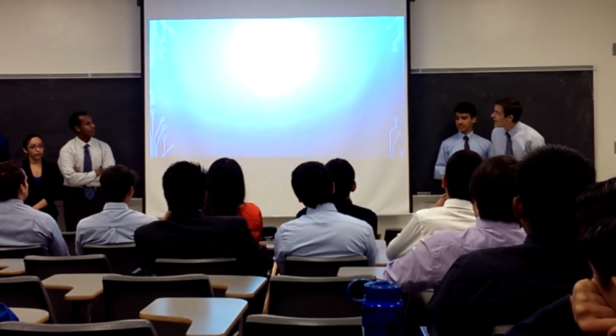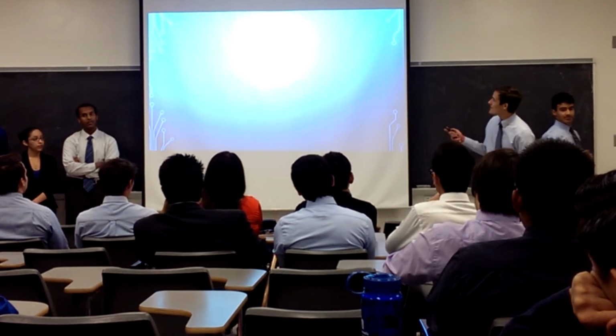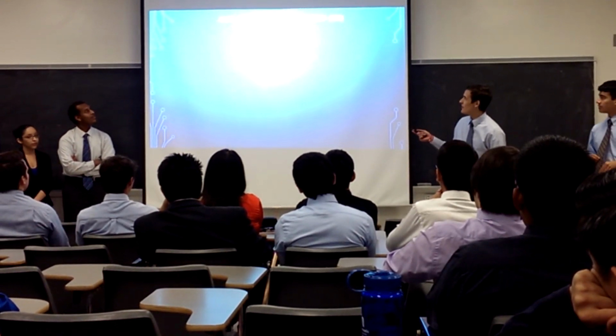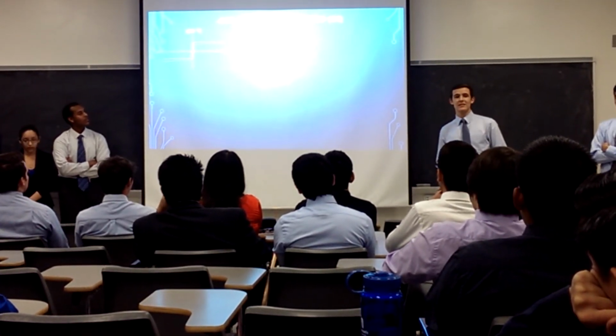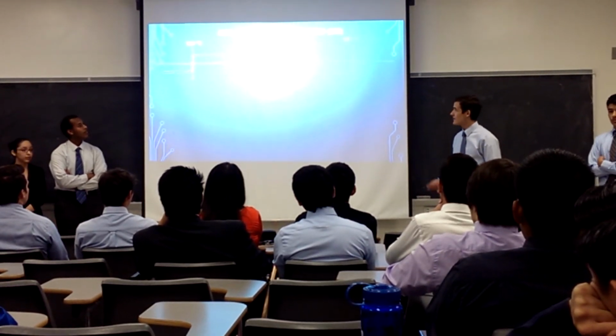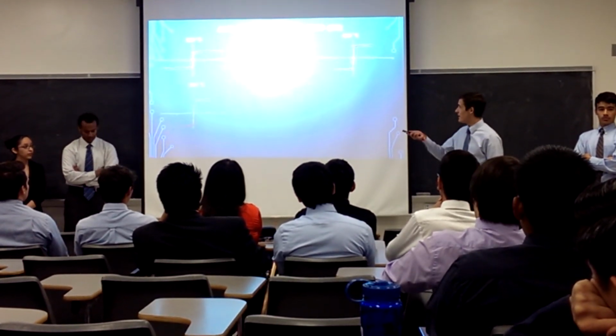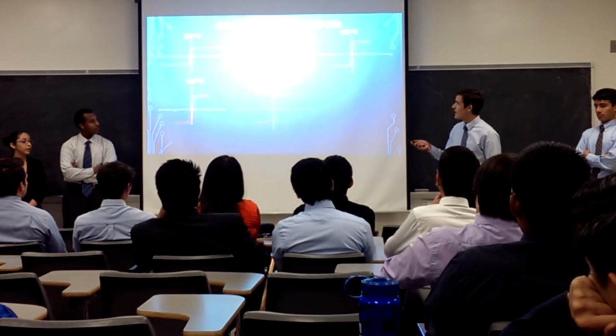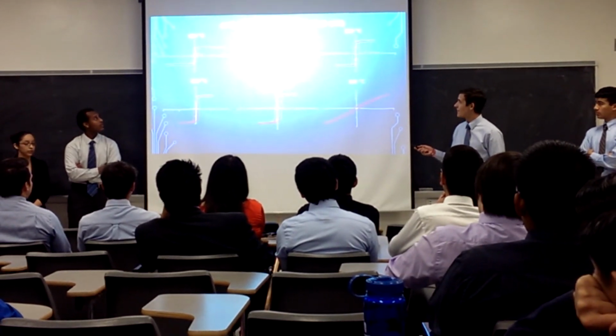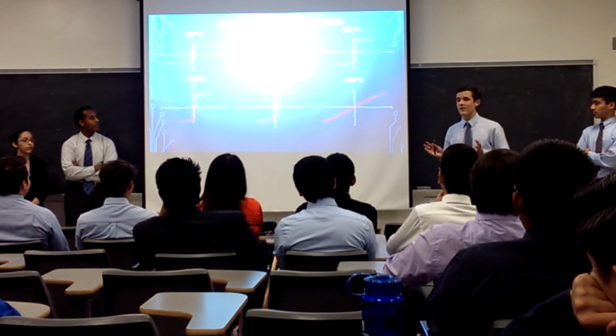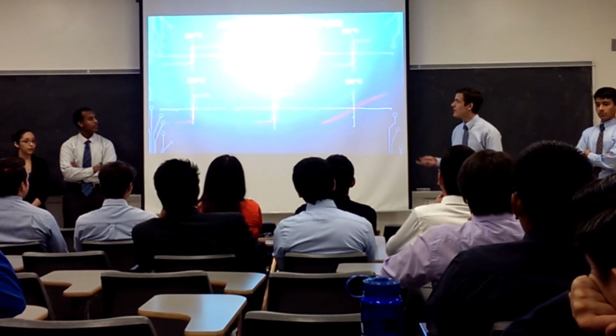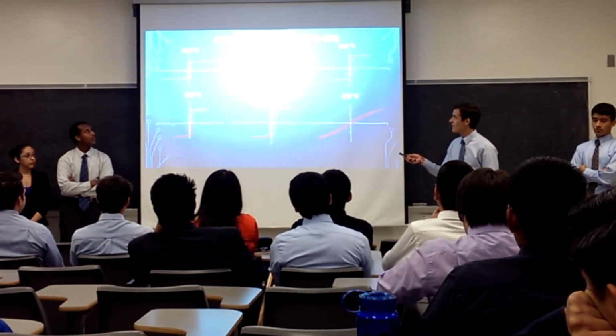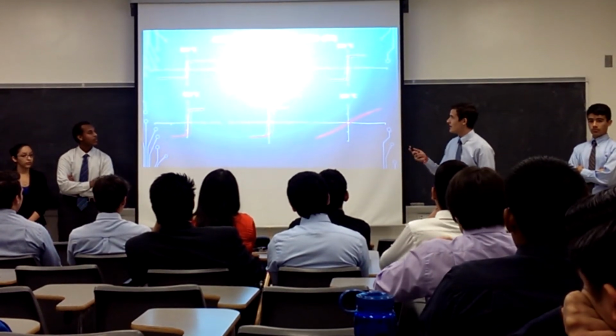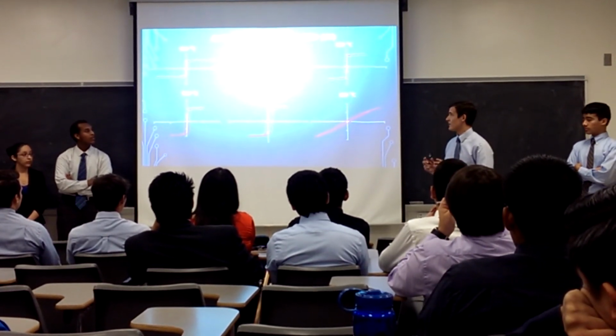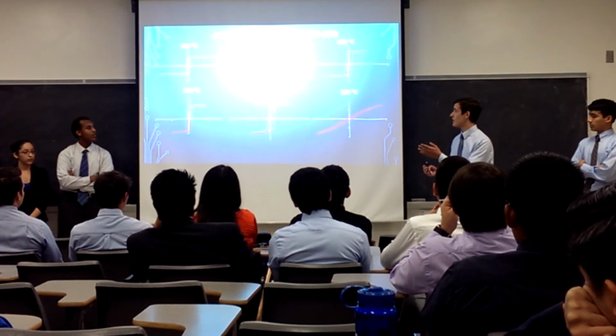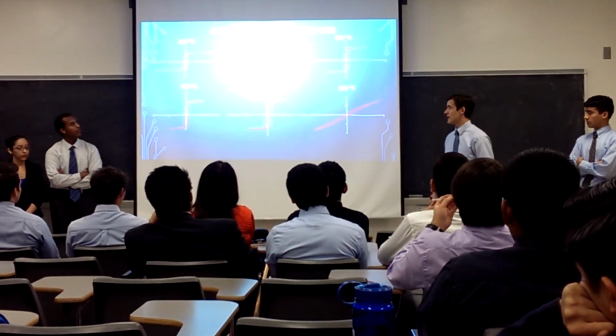Thank you, Byron. All right, so appearing up on the screen, we should have the results of the samples that we tested for exchange bias. So just to briefly describe what these graphs are showing, what each axis means, we're essentially plotting the average magnetic moment, which is a fancy way of saying the magnetization of our sample, against the applied magnetic field on the horizontal axis. And you can see that we did this for samples that were heated up to various temperatures, from 200 degrees Celsius up to 250 degrees Celsius.